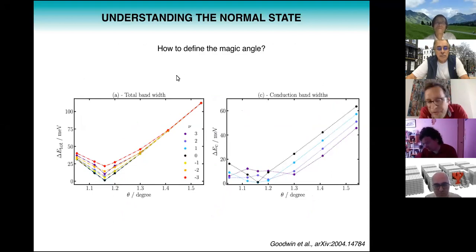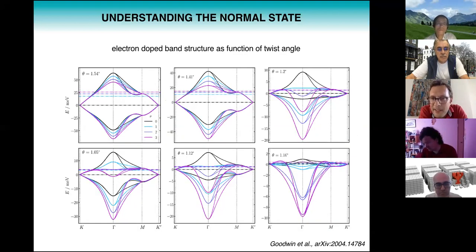And these new effects raise some interesting questions. In particular, you could ask, what is really the magic angle now? What is really the magic angle if I take electron-electron interactions into account? The flat band width that people often talk about, that's just a proxy, really. What matters, if you think about weak coupling theory, is basically the density of states at the Fermi level, right? Or you could say what is more closely related to the density of states at the Fermi level is actually the width of, let's say, the doped band.